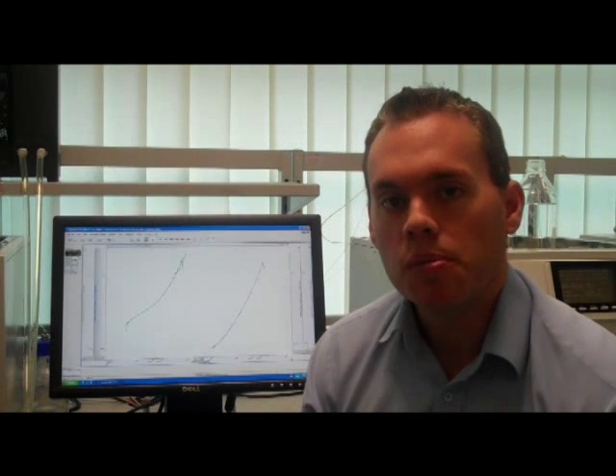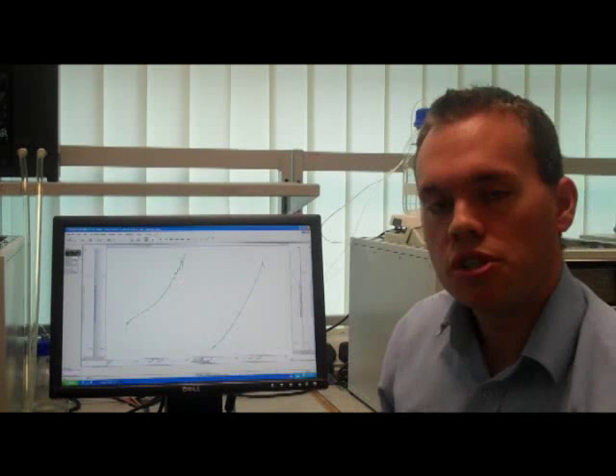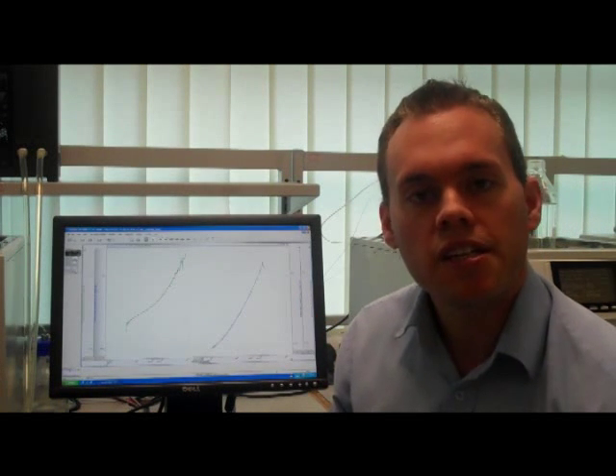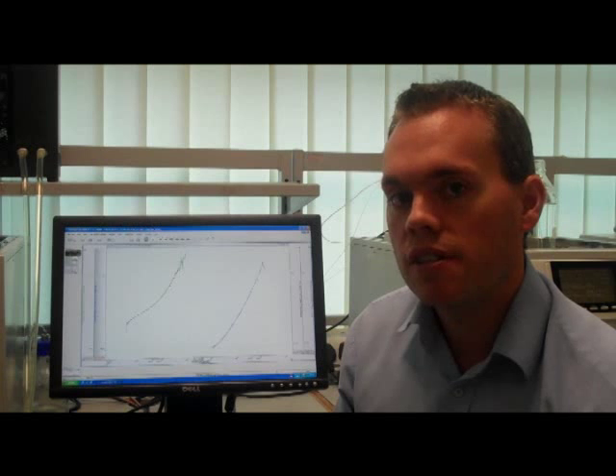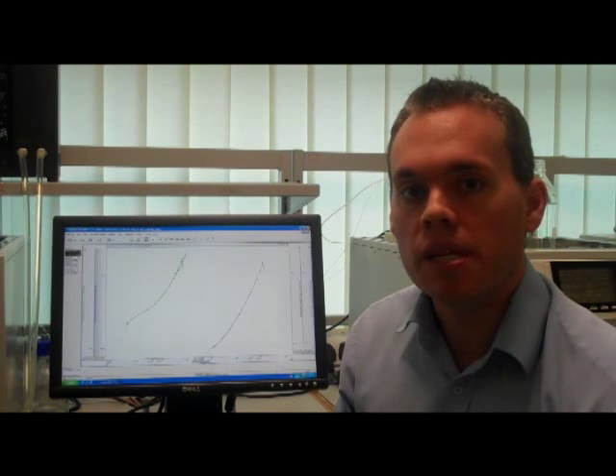But for the high molecular weight sample, we don't see this. We see a broadly similar intrinsic viscosity, which is actually considerably lower than we would expect if our first sample was simply showing an increase in molecular weight.